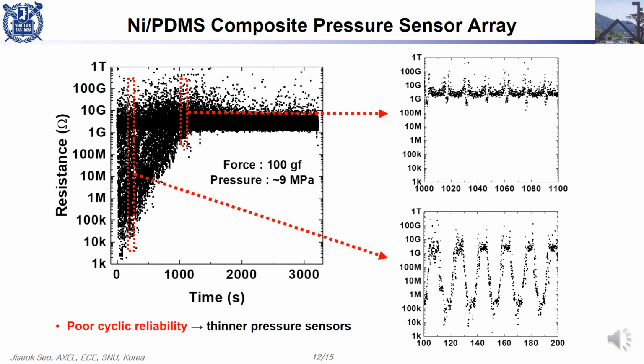This is the cyclic test result of the fabricated sensor arrays. Applied force is 100 gram force and the pressure is about 9 megapascal because of using sharp tip. At the early stages of cyclic test, the sensor showed good characteristics that the resistance changed from about 10 gigaohm to 10 kiloohm. However, when the cyclic test proceeded further, the resistance when the pressure is applied dramatically increased and the change of resistance was reduced.